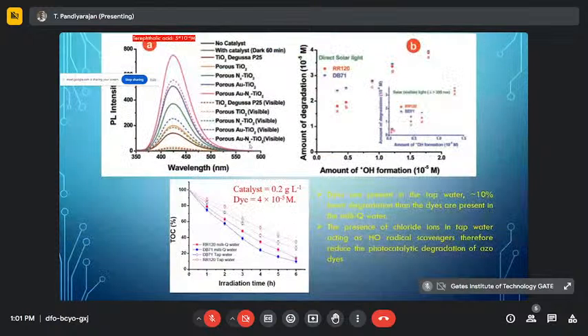Okay, and anyway we are going to use this in day-to-day life. So we have verified these dyes not in a controlled atmosphere like distilled water. If you use ordinary tap water in our home, in the tap water you have a lot of ions and minerals available. If you mix these dyes in the tap water, what will be the percentage of dye degradation using our preferred material? So we have done that analysis, and we have identified that almost 10% of the degradation was reduced compared to the double distilled water.